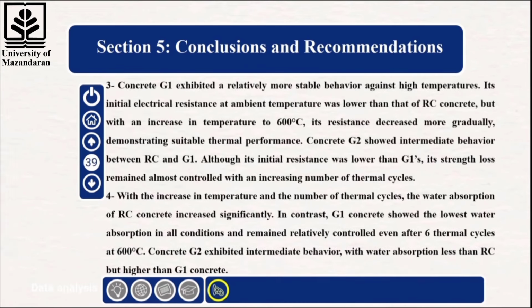3. G1 concrete demonstrated relatively stable behavior at elevated temperatures. Although its initial electrical resistivity at ambient temperature was lower than that of RC, its decline at 600 degrees Celsius was more gradual, indicating favorable thermal performance. G2 concrete exhibited intermediate behavior between RC and G1. Although its initial strength was lower than that of G1, the reduction in strength remained relatively controlled with an increasing number of thermal cycles.